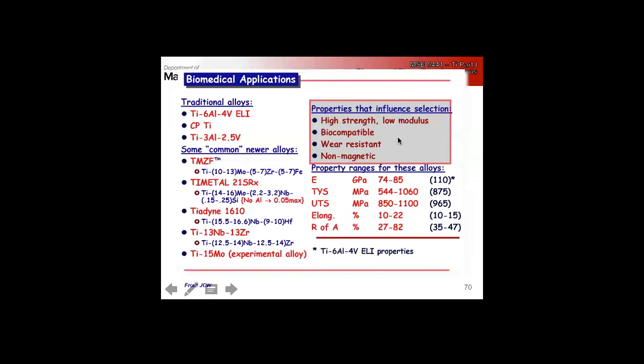These are the perfect sort of things. Corrosion resistant, not susceptible to hydrogen embrittlement, and it plays nice with the ceramics that are used. So alumina and yttria-stabilized zirconia, YSZ, are often used as part of biomedical implants for the knee joint. You'll have the implant, which is titanium, a ceramic ball, and then an ultra-high molecular weight polyethylene pad to give you your friction, to act like the artificial cartilage in your real knee. So it plays nice with all of those.